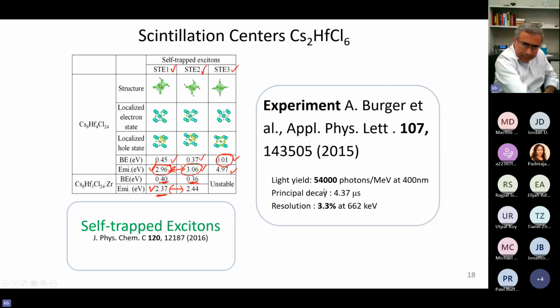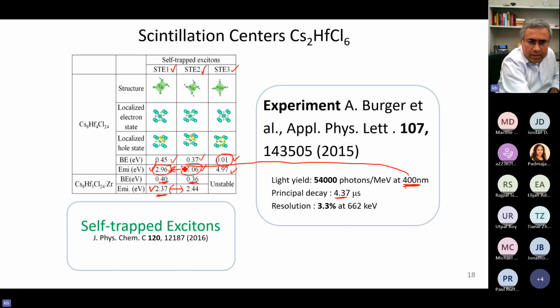They found that there is a principal decay time and a principal emission wavelength of, where is it? Right there, 400 nanometer. That 400 nanometer corresponds well with these two numbers right there. And I'm making a mess of my own slide, I know that, but that's how I do it. And so it corresponds very well with the hafnium related STE1 or STE2. So we thought that this could be the self-trapped mechanism of this self-activated scintillator.